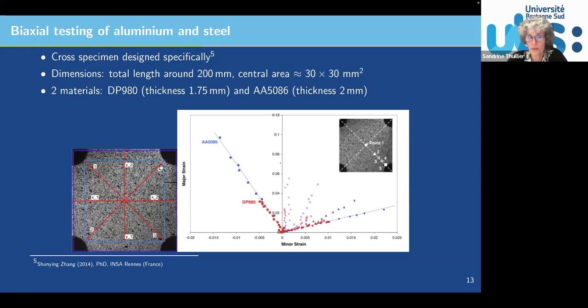And if you have a look here at the minor strain and major strain graph, you can see that, for example, in blue, this is for the aluminum alloy. You do have points along a line which is very close to uniaxial tension. You've got points close to biaxial tension, but you've also got points at several orientations. Meaning with only one test, you can cover all these kinds of homogeneous states. And this is the richness.